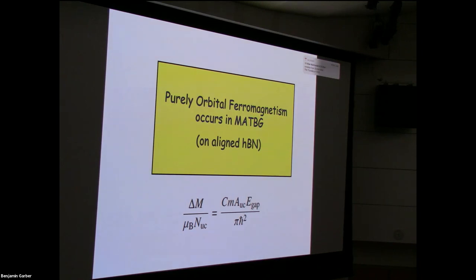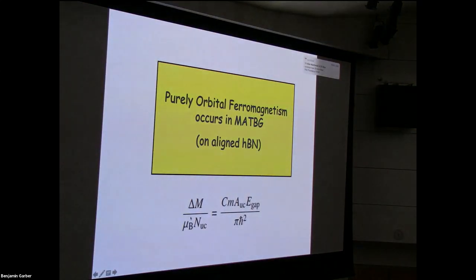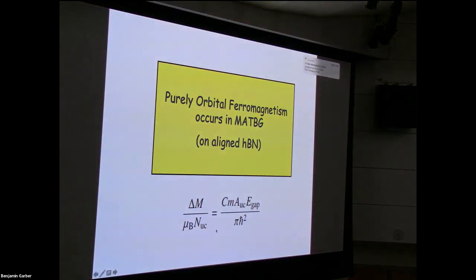Those edge states, even in equilibrium, are circulating around the system, and they produce a magnetization. If you change the chemical potential a little bit in the middle of the gap of this insulator, because there are always edge states, the magnetization can change. And it turns out that the size of this magnetization jump, from gating this insulator from weakly N-doped to weakly P-doped, is just fundamental constants times the energy gap. And this can easily be big enough to change the sign of the magnetization. The magnetization is orbitally dominated, and you can change the sign of it just by going from weakly N-doped to weakly P-doped, and this has been seen experimentally.